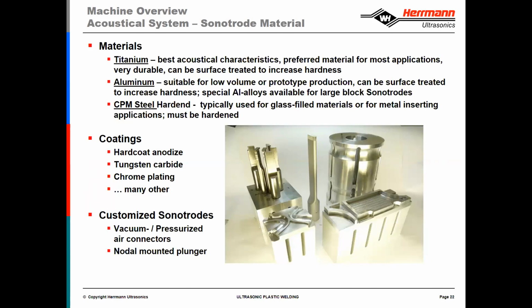If you have a glass-filled nylon, for example, and we've seen applications of glass-filled nylon up to as much as 30% glass fill, the glass fill is abrasive, so the tool can wear. The Sonotrode is making contact with that plastic part 20, 30, 35,000 times per second. Just as if you were to beat on something multiple times, it'll deform, it'll wear, it'll change. So we choose the material of the Sonotrode depending upon the material of the plastic part to be welded.